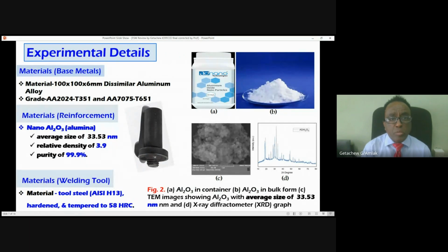When it comes to the experimental details, the first is the material under investigation: aluminum alloy plates with a size of 100 millimeters by 100 millimeters by 6 millimeters thickness. One is an aluminum alloy with copper as the principal alloying element, and the other is aluminum alloy 7075, whose principal alloying element is zinc. In both cases, the materials are supplied in the tempered condition, for better application.